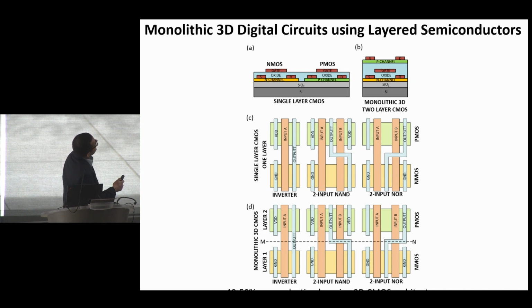So the idea here that we used was if you have a single layer CMOS, you have your NFET and PFET side by side, but you can start to, of course, stack one layer on top of the other. For example, you can stack the PMOS on top of the NMOS. Depending on what you're building, you can also share the gate, of course, between the two layers. And so this in some ways is similar to the concept of CFET that is being proposed beyond the current gate-all-around structure. And so using this approach, we built different digital circuits. This is how the layout looks for the different digital circuits that we built. If they were single layer, when we built them double layer, the way you can think about it is you fold it along this dashed line and you put the PMOS on top of the NMOS.